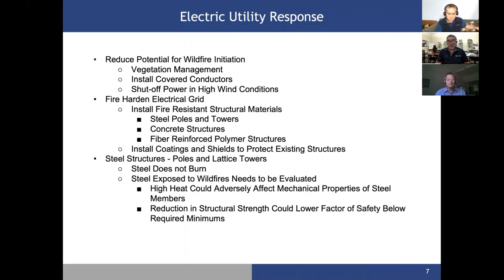So we're taking a two-pronged approach. We're reducing the potential for wildfire initiation, and we're trying to harden our system to protect it against wildfires in case one does start. One of the things that was a concern to us is that steel structures go through wildfires. While we know steel does not burn, we found out by discussions with Dr. Z that when exposed to high heat, it could change the material properties of steel. The high heat could adversely affect the material properties, such that it could make them brittle. It could lower the tensile strength of the steel. It could reduce the material strength, such that the design factor of safety of the structure may be below the required minimums that are needed by code.